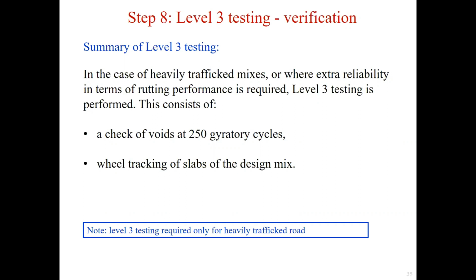It has two parts: the check of the air voids using a gyratory compactor at 250 cycles, and wheel tracking of the asphalt slabs.